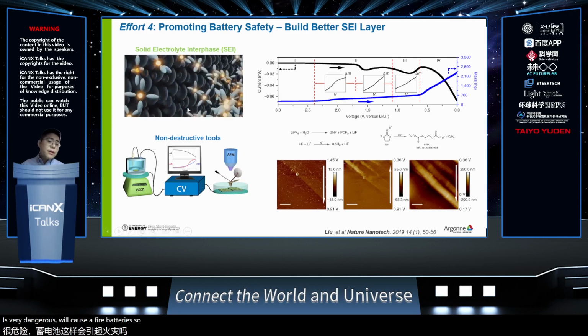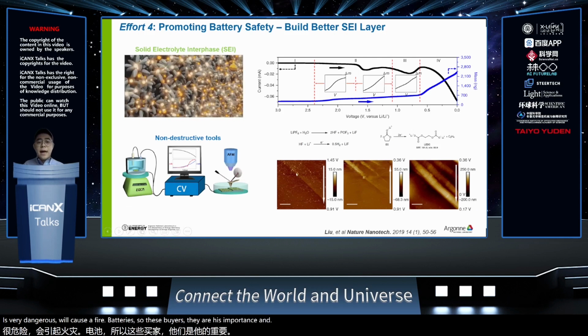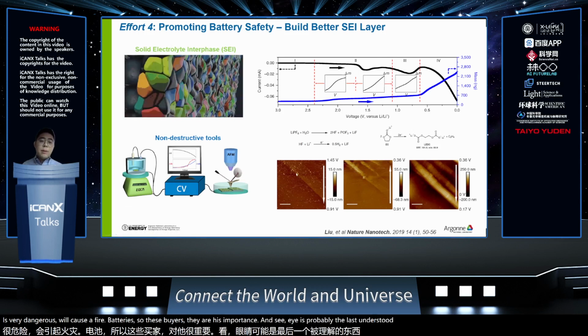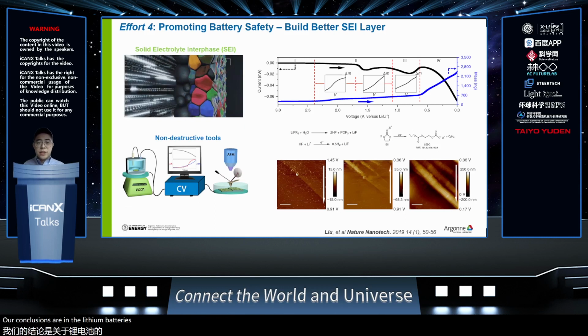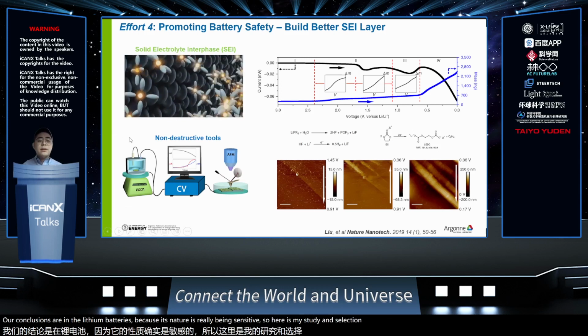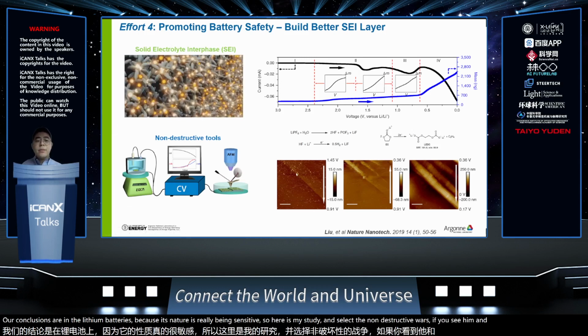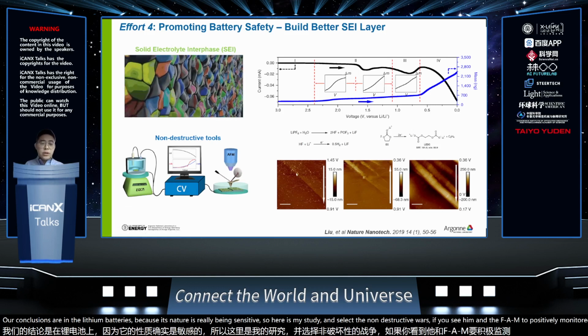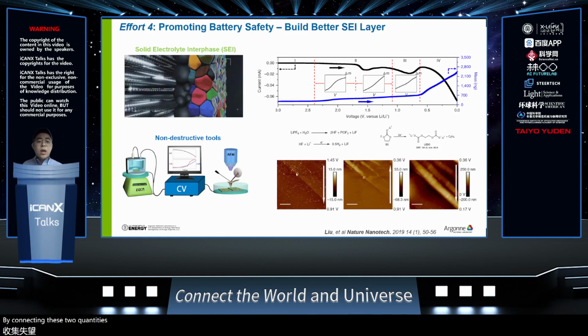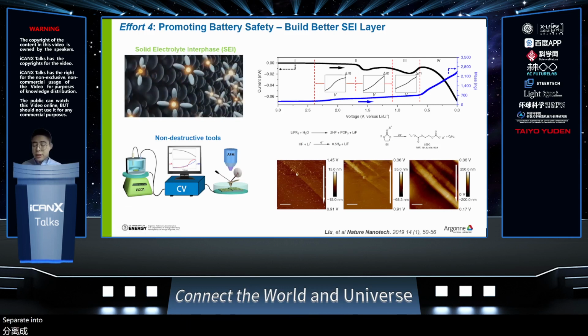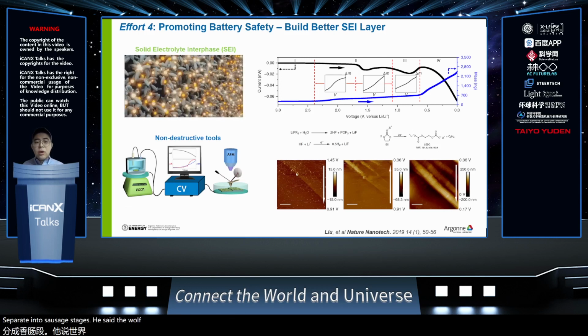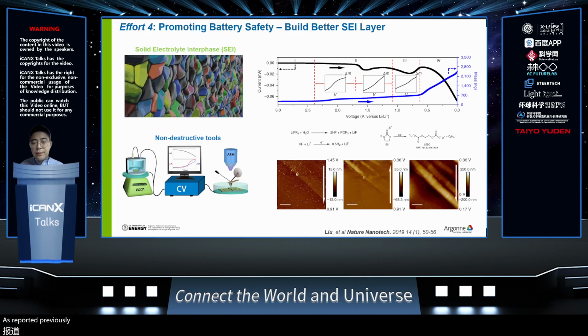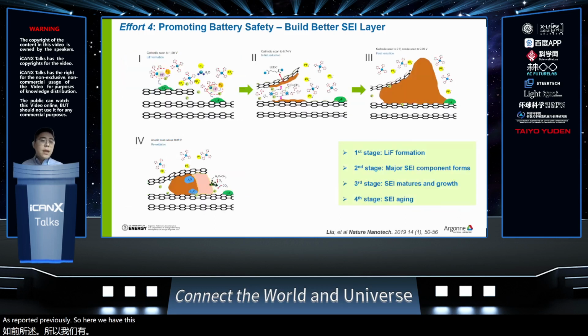Despite its importance, SEI is probably the least understood component in lithium batteries because its nature is really beam sensitive. So in my study, I selected non-destructive tools, EQCM and AFM, to quantitatively monitor the SEI formation. By collecting this quantitative information, we can conclude SEI formation separates into 4 stages instead of a single stage as reported previously. Here we have this figure to summarize our discovery.